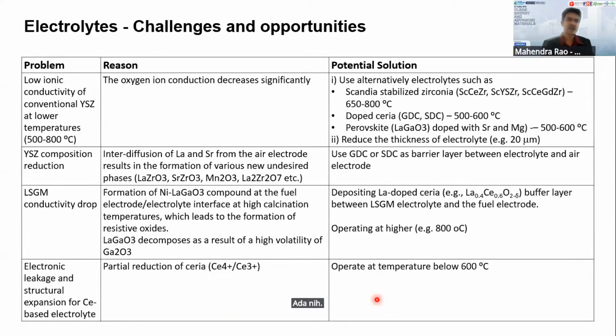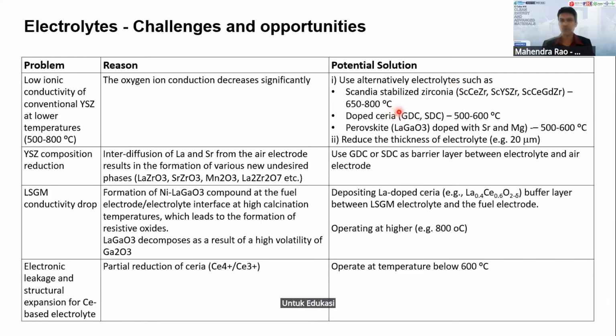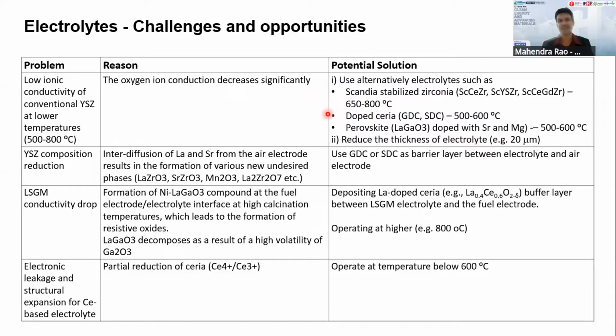And then in terms of electrolytes, as we know, the key for electrolytes is, as the first parameter, the conductivity. So oxygen ion conduction normally decreases significantly when you operate at a low temperature, especially for the zirconia-based material. So they propose an alternative material, scandia-doped zirconia-based material, but the challenge is the scandia. So where to get it? Scandia is expensive. So there is a geopolitical issue here to get the scandia. So this is the key consideration that we need to consider before we propose this type of material.